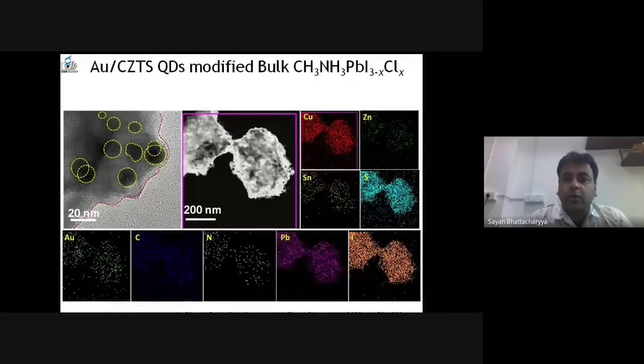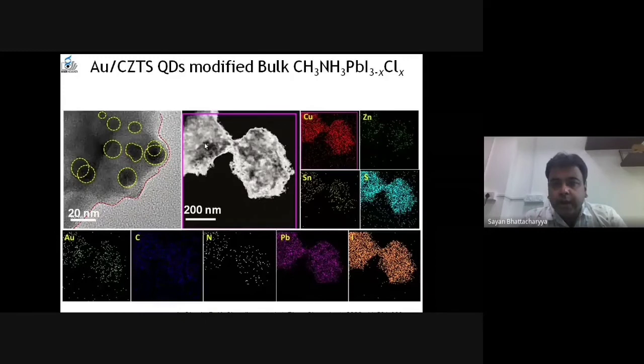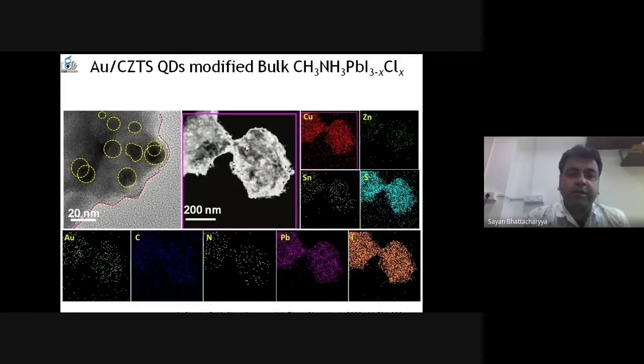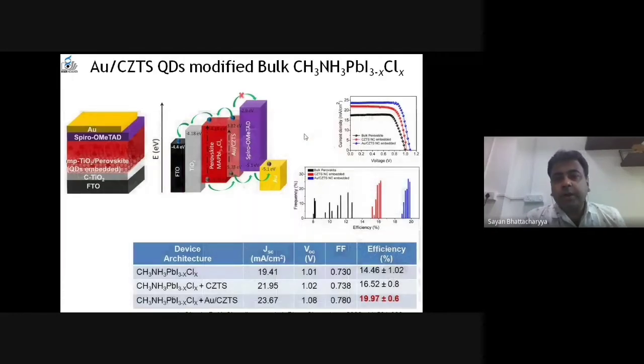And this is the electron microscope mapping. These are called STEM, scanning transmission electron microscope mapping, with dark field imaging. So here you can see that over this whole absorber layer, the quantum dot elements as well as the CZTS are all lying at the same time. So they are basically uniformly spaced. You can see these quantum dots which are here. So similarly, you need to have a band alignment, as I have already told you.